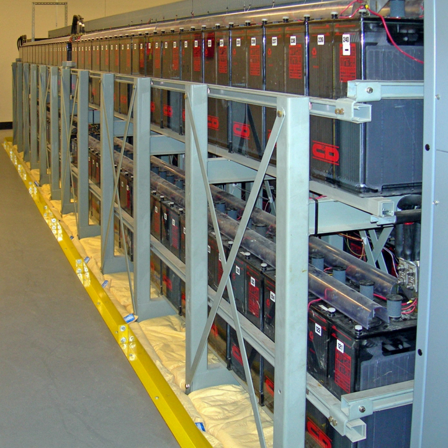The available capacity of electrochemical cells varies depending on the discharge rate. Some energy is lost in the internal resistance of cell components, plates, electrolyte, interconnections, and the rate of discharge is limited by the speed at which chemicals in the cell can move about. For lead-acid cells, the relationship between time and discharge rate is described by Peukert's law. A lead-acid cell that can no longer sustain a usable terminal voltage at a high current may still have usable capacity if discharged at a much lower rate.